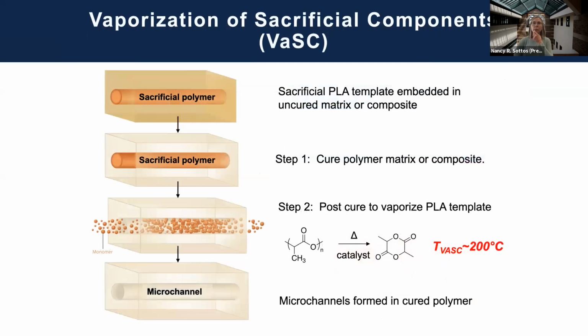Just to say a little bit about this process some more, we start out with a sacrificial polymer. In general, that polymer was polylactic acid, PLA, and we cure it in. And it survives the cure cycle, but then it needs a post-cure cycle to get rid of the sacrificial template, and ideally it vaporizes. And the vaporization temperature for some of our prior materials was about 200 C. I'll say a little bit about the timing on that. But when you're done, you get these beautiful microchannels in the polymer or the composite.